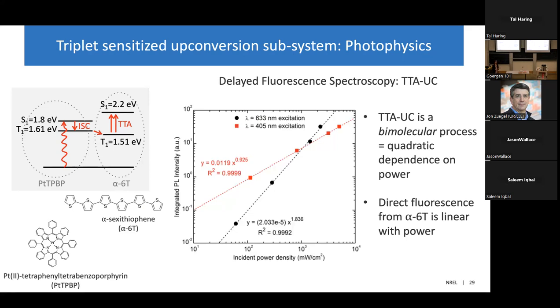Another test of triplet-triplet annihilation upconversion is to look at the power dependence of your emission. So triplet-triplet annihilation upconversion is a bimolecular process, so at least initially it has this quadratic dependence on your incident power. And when we plot the power dependence of our emission, which is shown in black, you can see that it has a log-log slope close to 2. So that is indicative of this bimolecular process. On the other hand, the direct fluorescence from alpha-6T is shown in red and has this classic linear dependence. All right, so we can be satisfied that this Jablonski diagram is correct in our system.